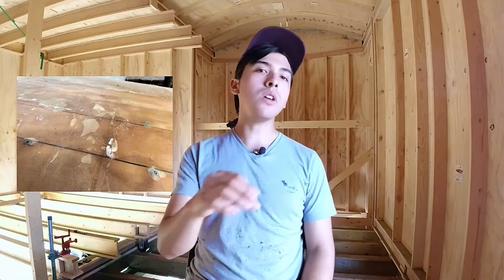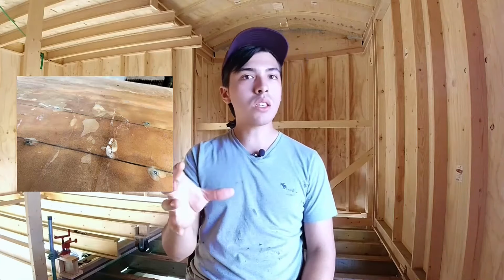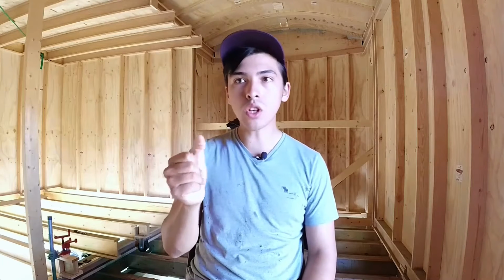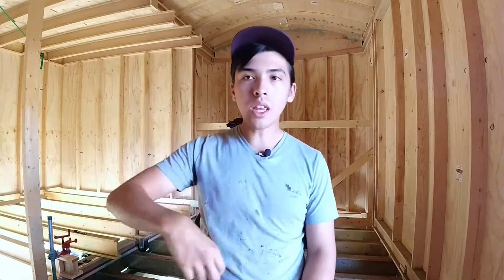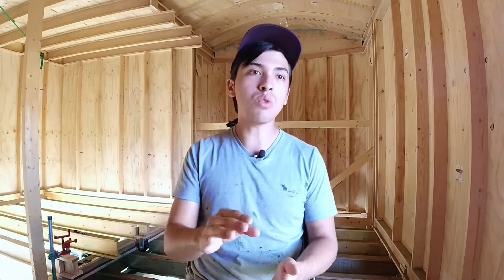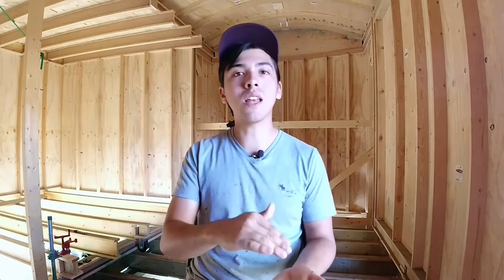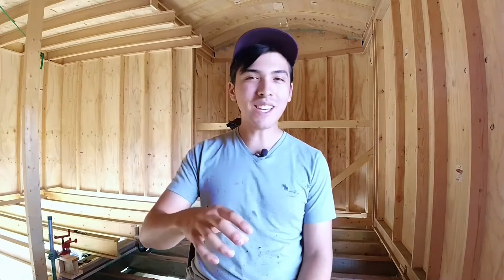You will probably end up finding that after you've done a whole job like this, you'll have some areas that did not work well. Maybe you'll have some air bubbles, maybe you'll have some spots that just didn't adhere very well, or the resin started curing too quickly and so it didn't stick to the wood super well. What you do in that case is just remove any loose material, sand everything, because the resin dries really smooth, and so new resin will not stick to that old resin. Make sure you sand it off, and then you just put on a new piece just as normal. As a matter of fact, that's another great reason to choose fiberglass as a roofing material, is that it's very easy to repair. If you do have a problem, just sand it off and put a new piece on.